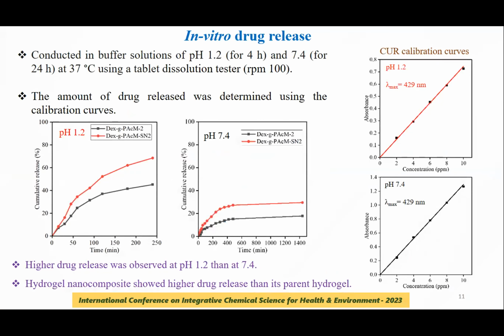We have taken these two different pH ranges to reflect the simulated gastric condition and simulated intestinal condition, because the application of this material is oral delivery of CUR. It mainly passes through the stomach, which is acidic in nature, and after that it goes to the small intestine, which is slightly basic in nature. We wanted to see at which pH value the material can swell significantly, because the drug release also depends on the swelling of the material. Once the polymer matrix relaxes, the drug can be released outside. In the same way in drug loading, once the material swells, the drug can diffuse into the polymer matrix. So we did this to reflect the real situation of oral administration of the drug, which is the stomach and intestinal tract.